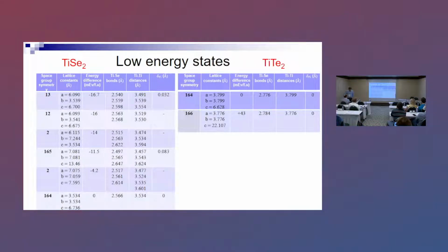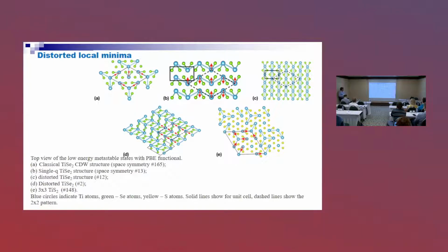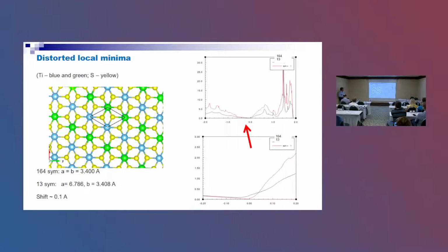Basically, what I want to say is that already on the level of the Coulomb interaction, the material has a preference towards a charge density or spin density wave. By this calculation, we can say there is an instability towards charge density wave. This is a distortion which can be presented as single Q, double Q, and triple Q structures. So basically, we haven't found any good semiconductor state. The best one is presented here, but nevertheless we didn't find one.